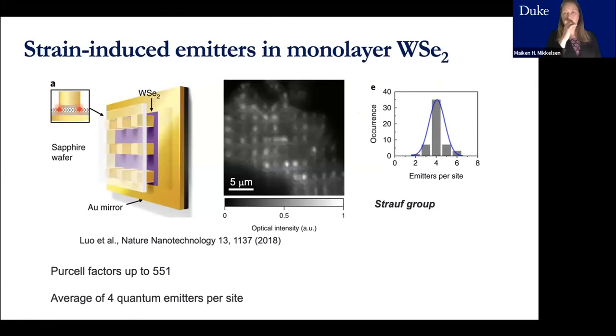And there's another example from the literature I wanted to share, with quantum emitters in monolayer tungsten diselenide. These are created by the strain of the nanocubes. I think this was a very clever idea. This was by Stefan Strauf's group, where they placed EBL-fabricated cubes, I believe, with a stamp onto the monolayer material, and that induced strain. So the red here is indicating the strain.